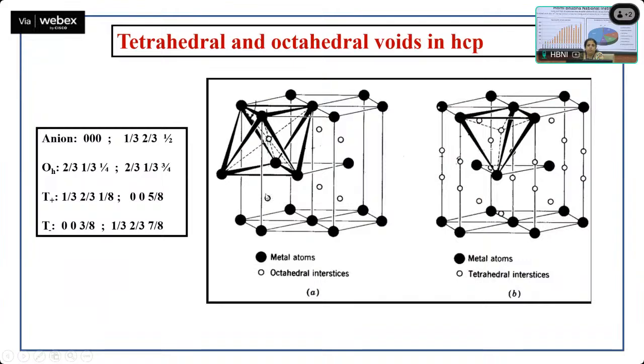Okay. So now I have to find the x, y and z coordinate for this particular site, which is the octahedral hole in hexagonal close packing. Now if this was half, this is 1z from this atom to this atom. So my layer B was at z equal to half. Obviously, the octahedral hole is at the center. So what is the z coordinate? That is 1 by 4.